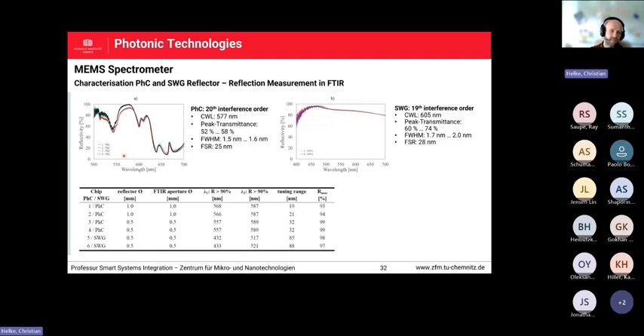And what you can see here, for example, is that we are in the range of 93 to 99% reflectance. The green and the black ones, and the blue and the red ones, are the two wafers I showed before with the two different opening diameters of, let's say, 10 nanometer below and 10 nanometer too large. And so it fits quite well to the simulation. We reach a reflectivity in a certain wavelength range, and we are quite happy. And also we could build some filters for this one and achieve a bandwidth of 1.5 to 1.6 nanometer. And for the SWG reflectors itself, we saw here that it's really broadband, also showing in the interesting range of 570 to 600 nanometer reflectance up to, I guess, 90%. So it will also work in this range.